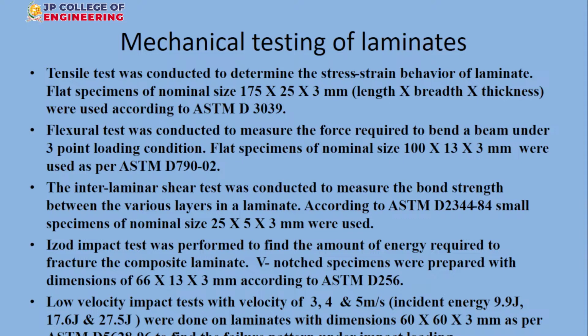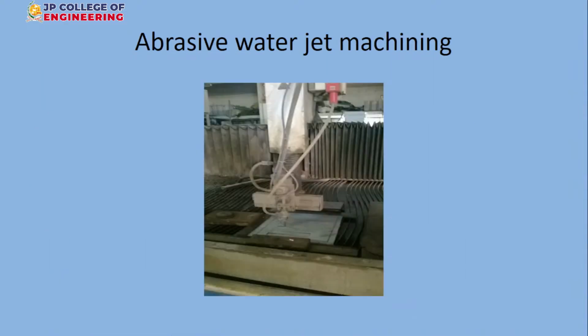So we have done mechanical testing: tensile test, flexural test, interlaminar shear test, impact test, and low velocity impact test. A simple Izod test, and also a low velocity drop height test, where a hammer falls on your laminate, and then we test. So all the tests we have performed. Again, all the specimens should be cut by abrasive water jet. Otherwise, if you cut with a hacksaw, it will not give a good value. So this is one of the points to be noted.